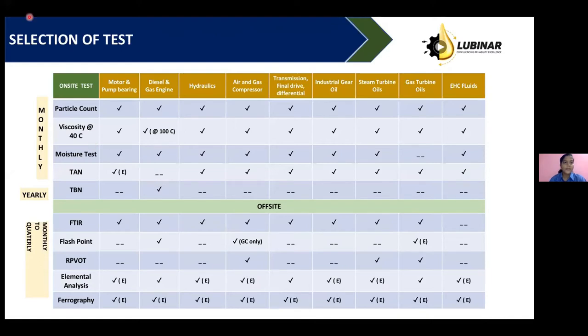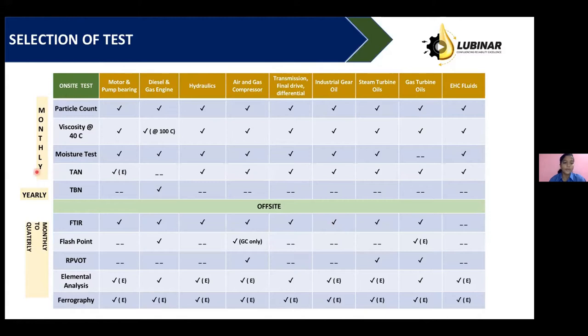Now that we have taken the sample, it's time for the selection of tests. This chart shows the oils, on-site tests, off-site tests, and their frequencies. The frequency and intervals of oil testing should always allow evaluation of wear generation, and should always be shorter than the MTBF — mean time between failures. For off-site tests: FTIR, flashpoint, RPVOT, elemental analysis, and ferrography should be performed in a dedicated laboratory by certified professionals.